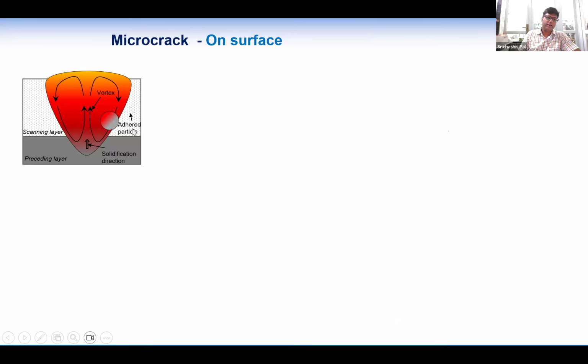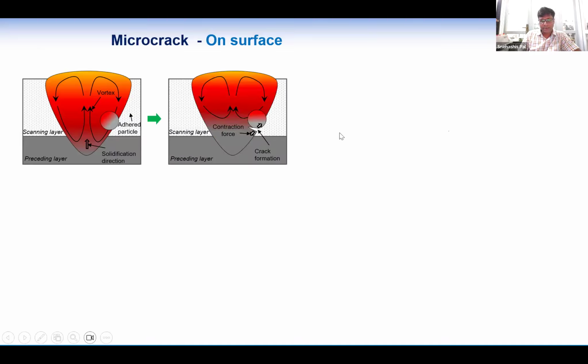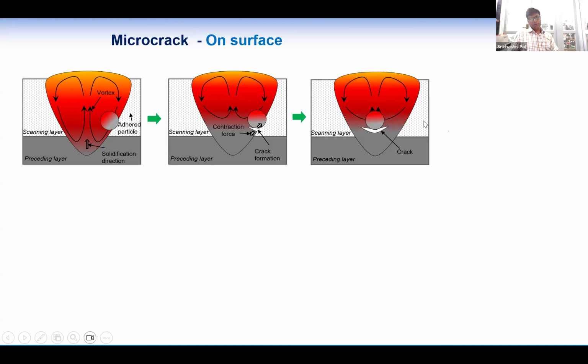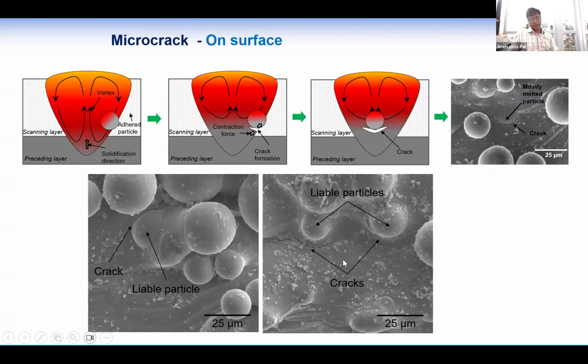There can also be some micro cracks. When a particle is partially melted on the melt pool, it can also go inside during the vortex. During cooling, the cooling starts from the bottom upward, so this portion cools faster. The shrinkage occurs much faster than in the particle, so a crack can initiate between them due to the thermal difference. In the front view it can look like this, and accordingly there are a lot of cracks on the surface.